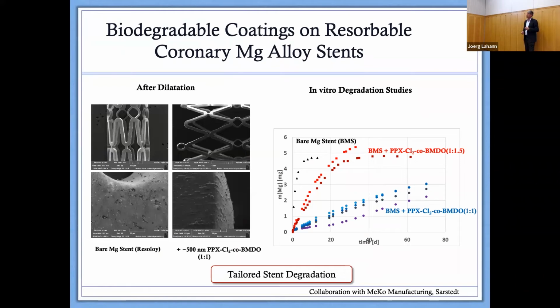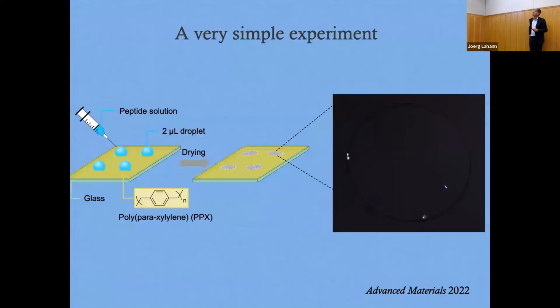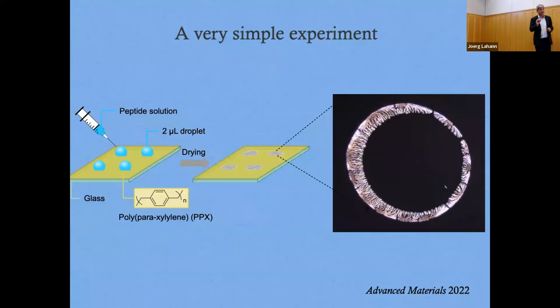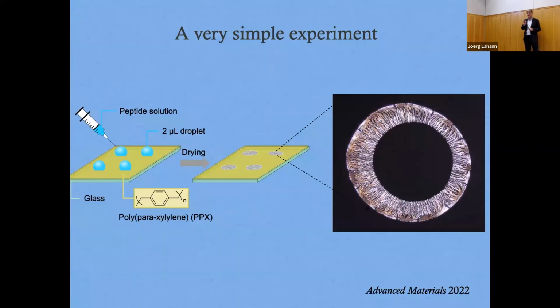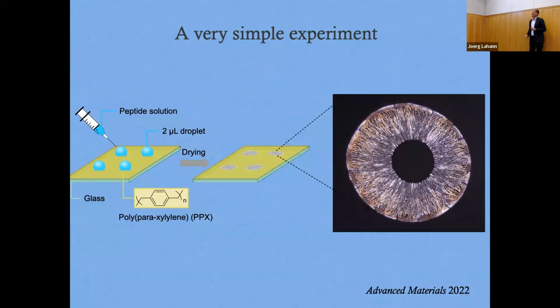We developed this a few years ago. And so we're basically modifying that to control the release kinetics of the magnesium stents, because in some instances, they release too fast or degrade too fast. And so we can tailor that with our polymer coatings. Okay. Now I'm going to give you one vignette, and the reason why it's there is this is where we use AI. So it's our AI approach, machine learning. So I thought I'd put that in.